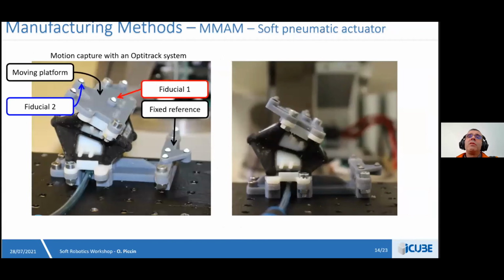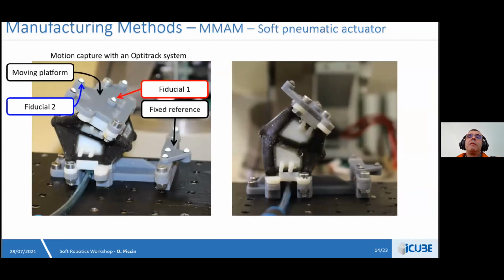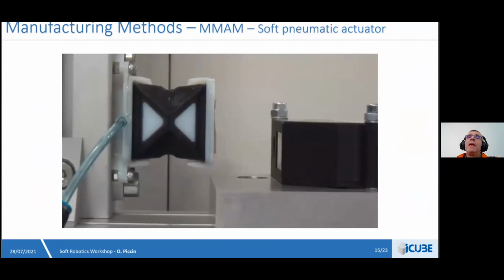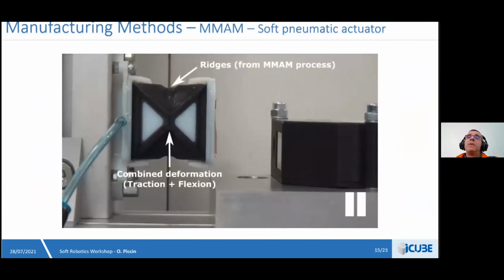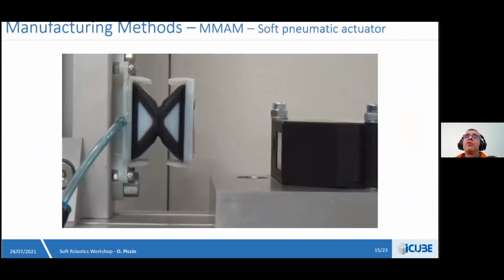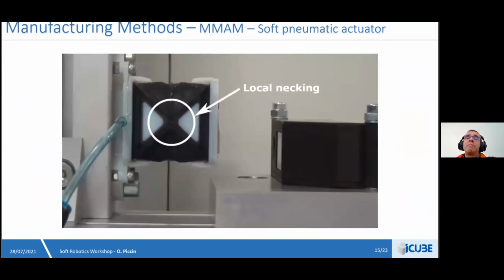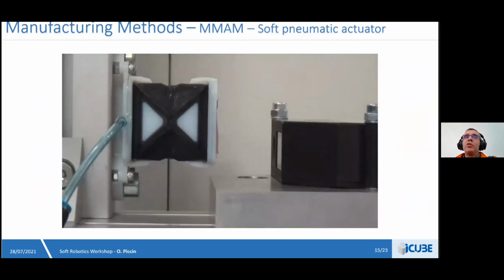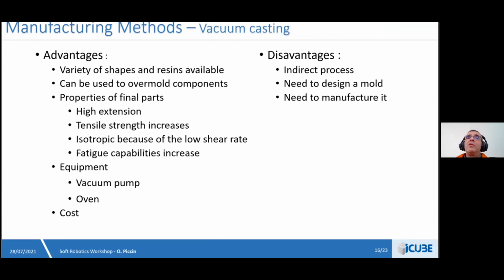We conducted different tests on the system. And in fact, what we arrived at is that when the system is operating, you can see ridges from the multi-material process with combined loadings, especially at the top of the closure caps. And if you push up the pressure, the system fails with a pressure in the order of 40 kilopascals. In this case, the soft material produced by the machine has quite limited strength compared to what could be done with regular silicone, if you have the capacity to produce with silicone.